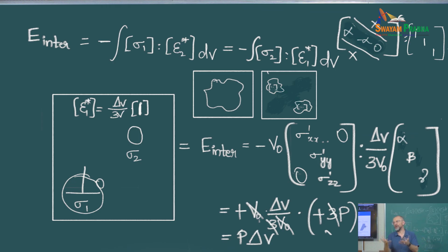When we have a spherical inclusion, we call it an Eshelby inclusion because it's the reference calculation. What I've shown here is just a generalization of what he has done, and you recover exactly the same result using what we have seen this morning. It's just a name that we gave in the community. When you say you are looking at an Eshelby inclusion, people will already know that you're looking at a spherical precipitate with a volume misfit with the matrix.